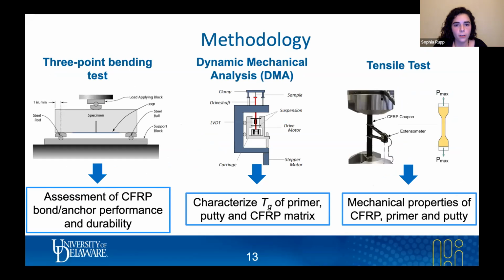We will be measuring the strength of both the SLC and the ACP groups by doing a 3-point bending test. The beams that I casted so far are 6 inches high by 6 inches wide by 20 inches long. And when they are applied to the 3-point bending test, they will have a clear span of 18 inches. There will be a point load applied on the compression face of the beam at midspan. And on top of this, there's also a notch introduced at the tension face at the center line, so that we can control crack initiation. From this test, we will be able to collect information about load versus deflection. And on top of that, we will be able to collect strain data from the CFRP. The strain gauge will be applied on the CFRP sheet, and it will be applied over that crack that's introduced.